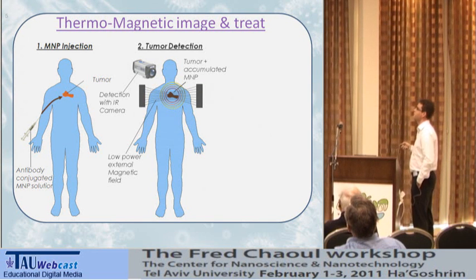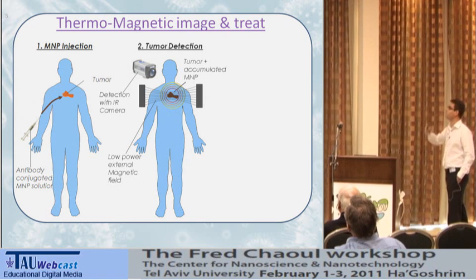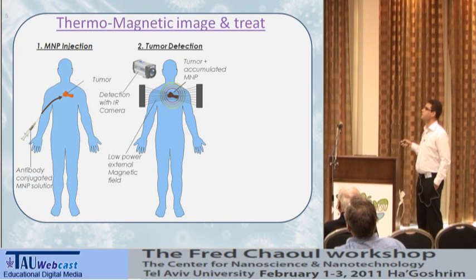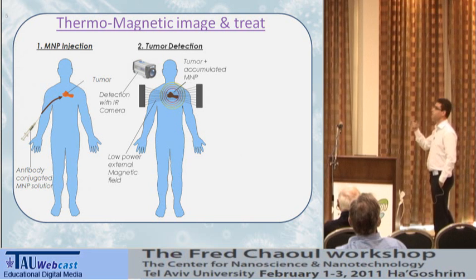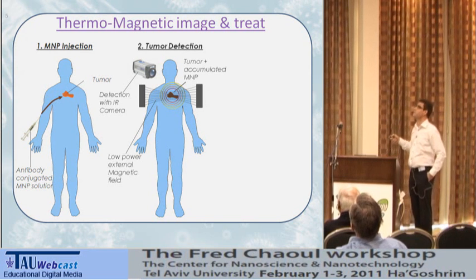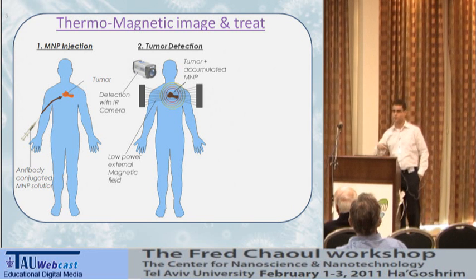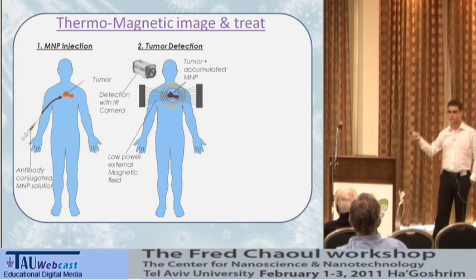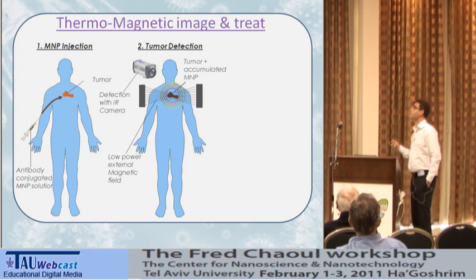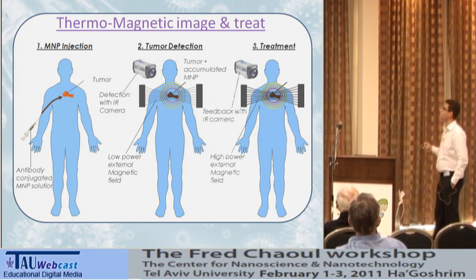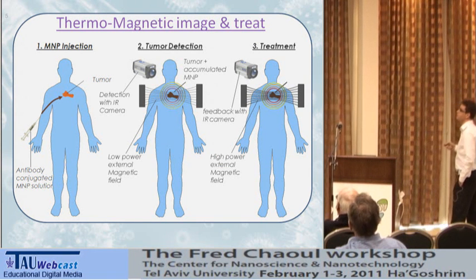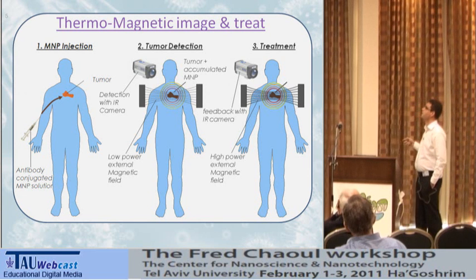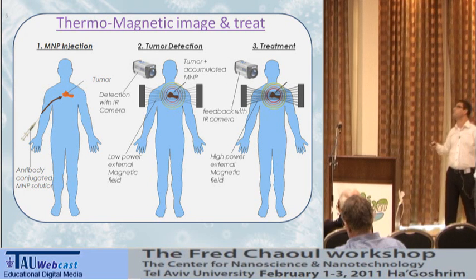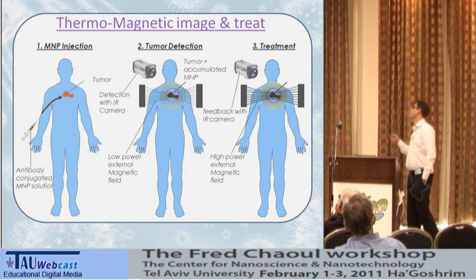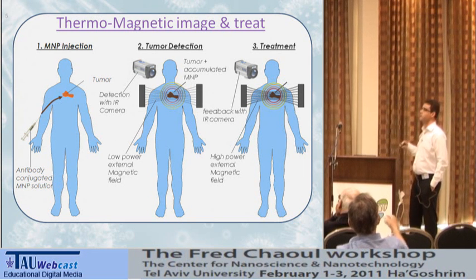Then after a few hours, we apply an oscillating magnetic field. If there is some accumulation of nanoparticles, they will start to heat. They will generate heat that will dissipate through the tissues and reach the skin surface. On the skin surface, we can use an IR camera to observe the temperature pattern that develops. And we can detect whether there's a tumor or not, and if so, what is the location of the tumor. Furthermore, once a tumor is located, we can increase the field strength and treat the tumor. We can specifically hit the tumor up to a point that it is killed, or at least we disrupt the biological processes in there, and at the same time use the IR camera as a feedback mechanism.